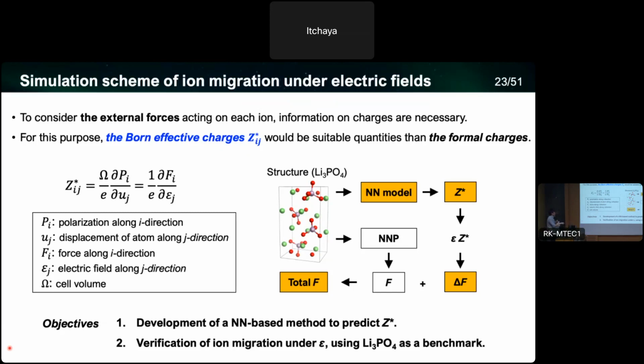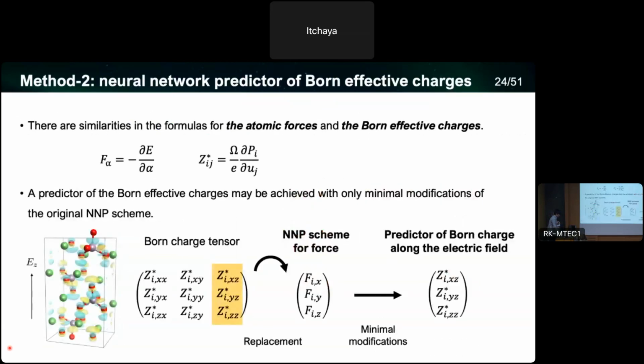The objective of this study is, first, to develop this model and also verify the ion migration under the electric field using Li3PO4 as a benchmark material. And this is a bit technical, but we just want to achieve this kind of model with the minimal modification from the original neural network potential. So we focus on the similarity in the equation of atomic forces and also the Born effective charges.